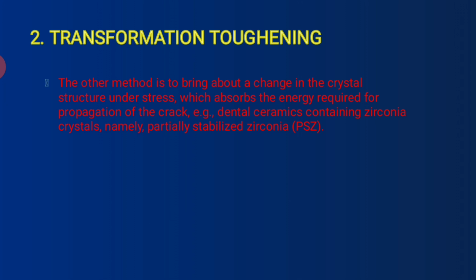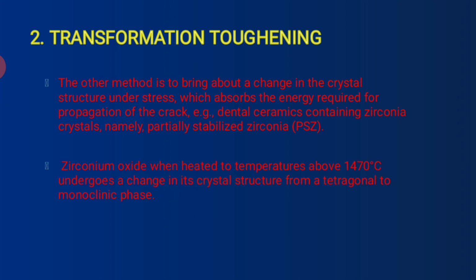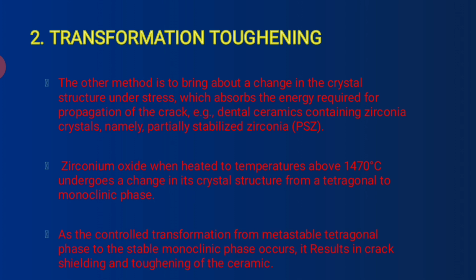Example: dental ceramics containing zirconia crystals, namely partially stabilized zirconia. Zirconium oxide, when heated to temperature above 1470 degrees Celsius, undergoes a change in its crystal structure from a tetragonal to monoclinic phase. As the controlled transformation from metastable tetragonal phase to stable monoclinic phase occurs, it results in crack shielding and toughening of the ceramic.